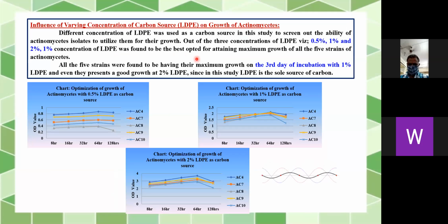Influence of varying concentration of carbon source. Different concentrations of LDPE were used as a carbon source in the study to screen the ability of actinomycetes to utilize them for their growth. Out of three concentrations, 0.5, 1, and 2%, 1% LDPE was found to be best for attaining maximum growth for all five strains of actinomycetes, and all five strains had their maximum growth on the third day of incubation with 1% LDPE.